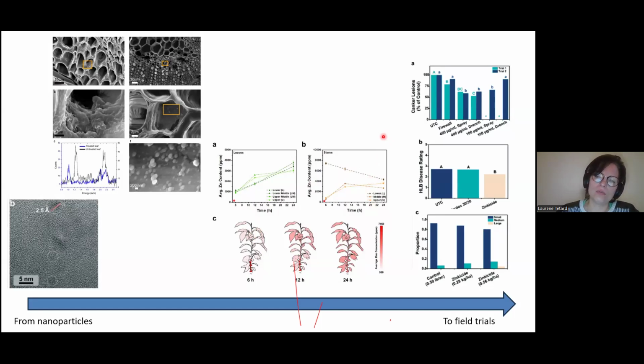And so I think the really exciting part of this project was that we really started from the nanoparticle, a few nanometers in size. We went to the seedling side and the bacteria culture level. And then we also worked with people in greenhouses and field, and they did extensive greenhouse and field trials to show that the same treatments that we studied at those smaller scales have an impact on the size of the fruits, on the HLB disease rating in the field, and also at the time we looked at canker lesions and showed that those different treatments have an effect on that as well. So this really took the entire scale from nanoparticle to really nanotechnology, from the synthesis to the characterization all the way to the field.